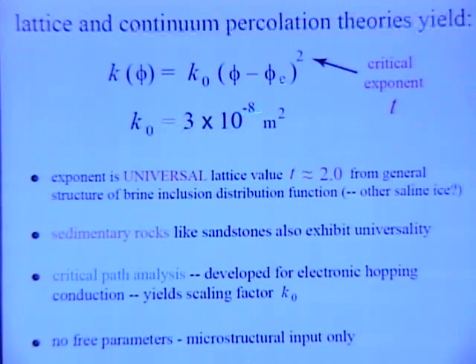And so this is our deceptively simple prediction, a simple formula for the fluid permeability and how it depends on volume fraction. And this scaling constant in front we actually compute as well using so-called critical path analysis, which was originally developed for electronic hopping conduction in doped semiconductors. And so again, we get this universal lattice critical exponent. This is our prediction here.